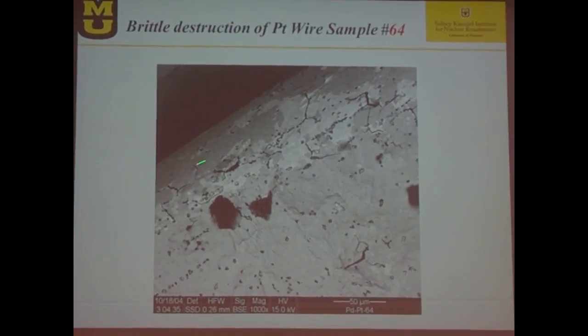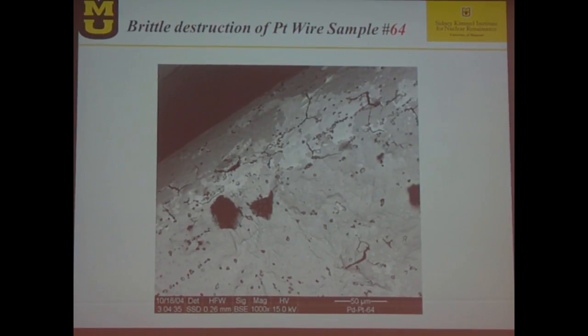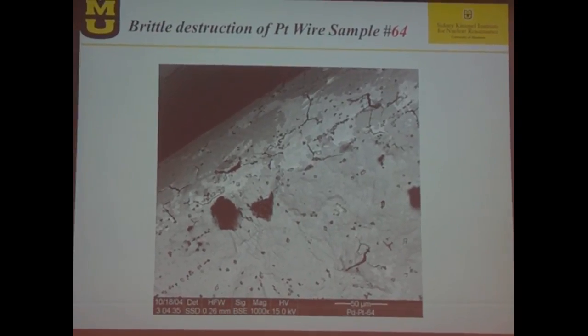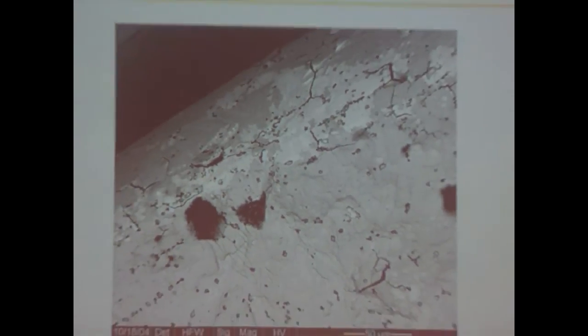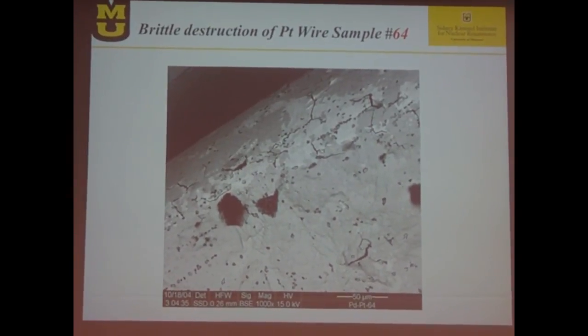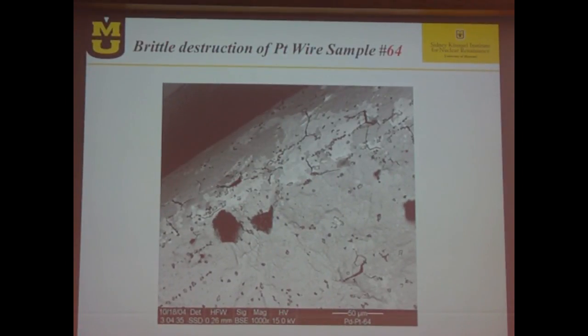Another peculiarity, look, this is the platinum wire which is connected in order to measure the resistance, 4 wires measuring the resistance on the cathode, and another wire for delivering the current. Look what happened to the platinum. Usually it's smooth, and the temperatures were so high on the cathode that the Teflon, which is insulating the wires, was burnt off along 2-3 centimeters close to the cathode. People were claiming maybe your current was so high that you didn't know about that. If this is true, and if you calculate the resistance of the platinum wires as compared to the cathode, the whole wire with its insulation was supposed to burn off, but it wasn't. It was just close to the cathode.